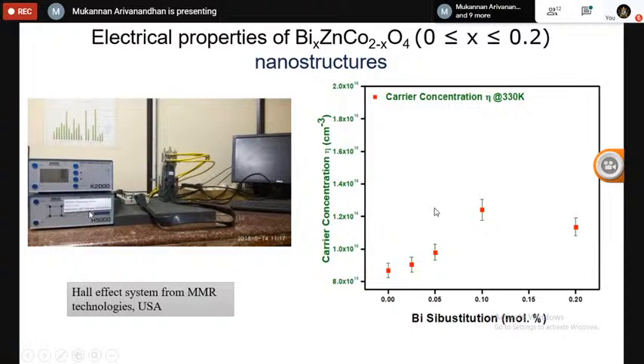is measured by using the Hall effect system, and the carrier concentration has increased with respect to the bismuth content up to 10%, and then slightly decreased at the high bismuth content. That's mainly due to the formation of the secondary phase.